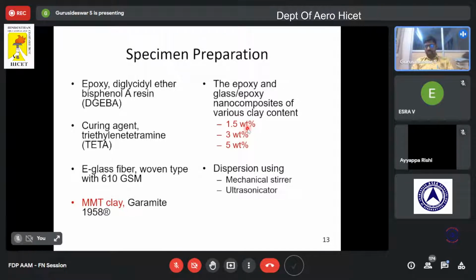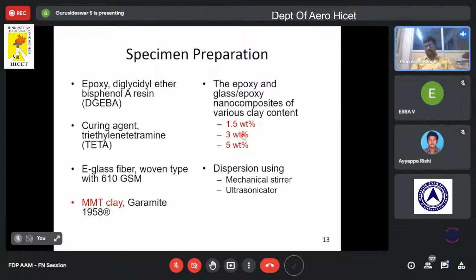For example, 1.5 weight percentage means we take 100 gram of resin and we take 1.5 gram of nano clay, and then the clay has been mixed with epoxy. So we took 3 different weight percentages of clay to fabricate the nanocomposite samples. Again, we use a mechanical stirrer to disperse the nano clay with epoxy. We have done some optimization of the spindle type, the dispersion time, and the speed of the spindle. We have optimized the parameters, and then we were able to disperse the nano clay in the epoxy matrix.